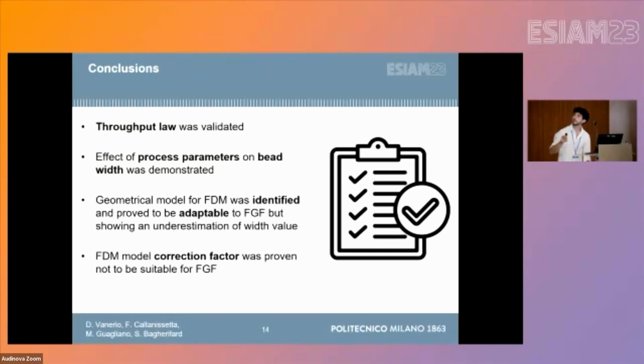To conclude, we first of all obtained and validated a model for the throughput law. Then we analyzed the effect of the process parameters on the bead width, which were as expected, and we identified the geometrical model for FDM, which can be adapted to FGF. But at the moment we have an underestimation of the throughput value, or we have something in the geometrical model, which is the other option, that makes the expected width smaller than the experimental one. So we have to find a more appropriate correction factor, because the one for FDM was proven not to be suitable for FGF.